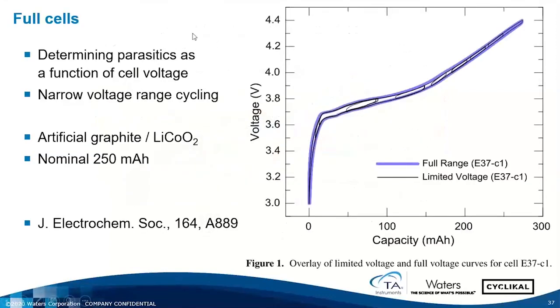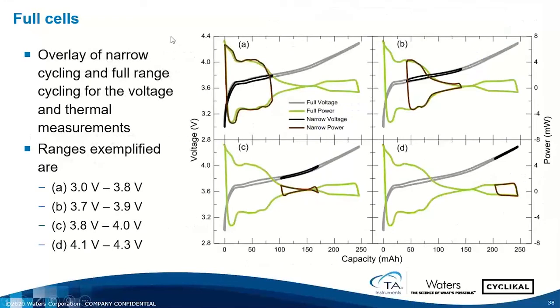Full cells. All right, so this is what we did to work out the parasitics as a function of state of charge. So we're doing narrow voltage range cycling. It's artificial graphite with lithiated cobalt oxide, and the nominal capacity is 250 milliamp hours. And this is a pouch cell. Over here, you see the full voltage curve. And what we're going to do, we're going to take bite-sized pieces of this voltage curve and cycle within those bite-sized pieces. So you see one here, one here, one here, etc. So we do approximately 10 cycles in these ranges, calculate the average thermal power, and plot that against the average voltage of that segment.